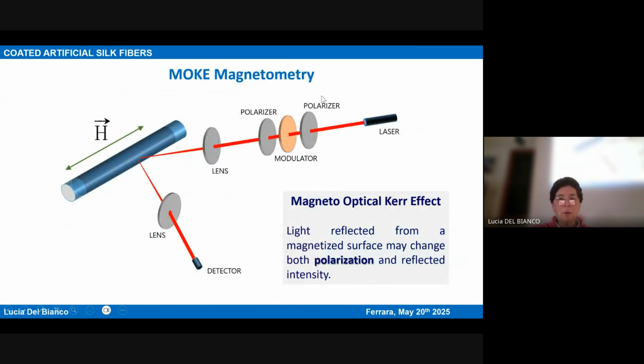And here, the suitable technique is also here in the department. It is MOKE magnetometry. It's a very particular kind of magnetometry, which is based on the magneto-optical Kerr effect, which means that polarized light reflected from a magnetized surface may change its polarization. And therefore, if you apply a magnetic field which changes the magnetization, you can measure the magnetization changes by looking at the polarization changes. But here again, I'm speaking of one single fiber, okay? One single fiber, a piece of single fiber. So it seems really difficult, but it can be done.